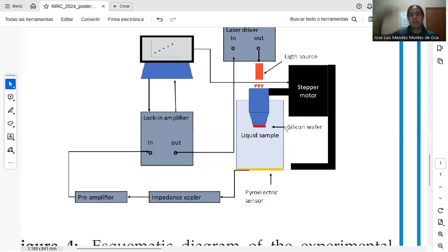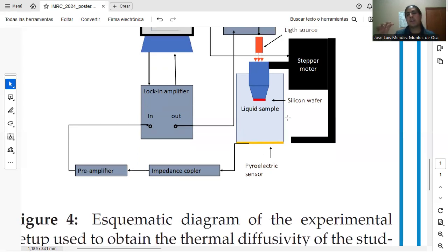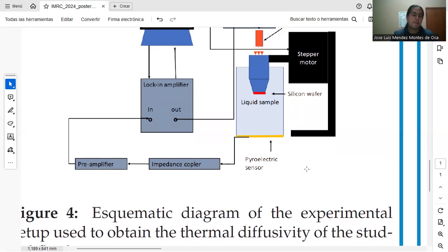And the silicon wafer is immersed in the liquid sample, which is located here, in a chamber. And the silicon wafer is attached to a cylinder, which can be moved up or down using a stepper motor. And so this is equivalent to having different thicknesses of the material. At the bottom of the liquid sample chamber, there is a pyroelectric sensor with which we can obtain the signal with the information of the temperature changes in the material.